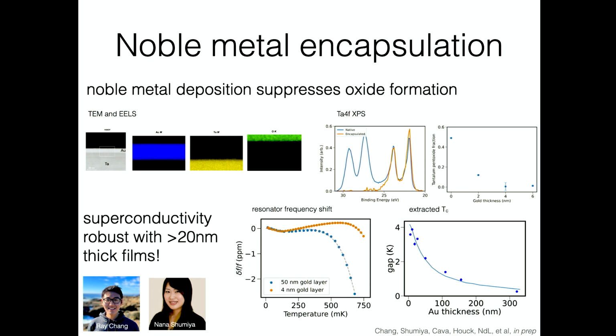And then if we use these resonator measurements to extract what the effective critical temperature is, we see that at this 4 nanometers, we only see a very small suppression in TC. And we can even see superconductivity out to 100 nanometers of gold on 200 nanometers of tantalum, which is really remarkable. And this is all led by Ray Chang and Nana Shumiya in my group.